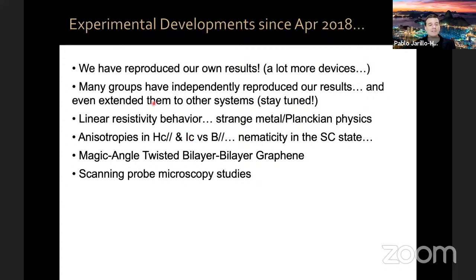Many, many other things have been obtained. For example, the resistivity of magic angle graphene is linear in temperature above the correlated region in density. This leads to behavior which is very reminiscent of the strange metal and Planckian physics behavior in other correlated systems. Several groups have measured anisotropies in the system, in particular in our case, anisotropies in the critical parallel magnetic field and in the critical current versus parallel magnetic field. These are indications of nematicity in the superconducting state of the system, which points to a possible unconventional order parameter.